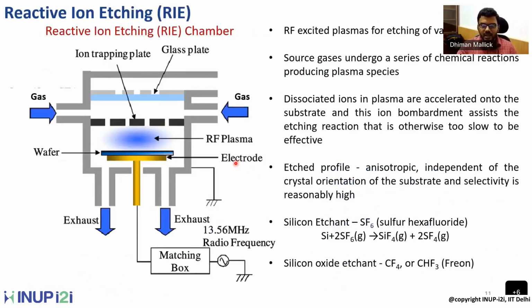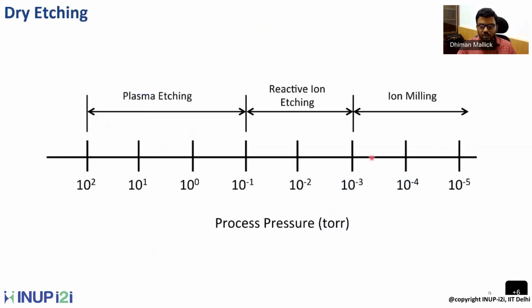So what is happening? When the pressure is low, as in the ion milling process, the mean free path for ion transfer is quite long. So the ions get transferred to the wafer surface without any collision or with very little collision. Their momentum transfer is quite direct, and quite high in nature. Whereas in plasma etching, this momentum transfer is not that important. There the chemical reaction is mainly important, and the mean free path is quite low.